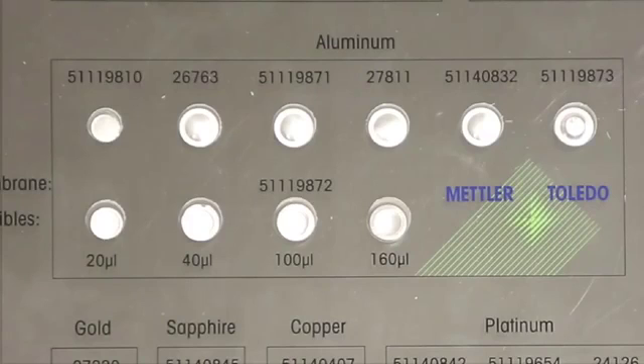per minute. If self-generated atmosphere above the sample is desired, use a special perforated aluminum lid with laser-cut 50 micrometer hole. This is sometimes necessary to shift evaporation or for boiling point studies. Take care that the welding occurs evenly distributed on the crucible rim.